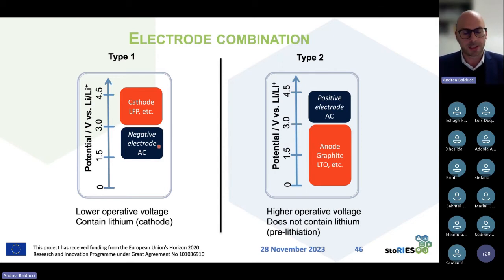The limit of this system is that they will not have a very high operating voltage, so 3 volt. So again, this will not be very convenient, because it would probably not give us the chance to have a very good performance. But another possibility, which is more interesting, is actually to combine a graphite, so an anode of lithium-ion battery working at a very low potential, with an activated carbon. Now, this combination is very interesting because we could reach devices that are above 4 volt, so a very high cell voltage.